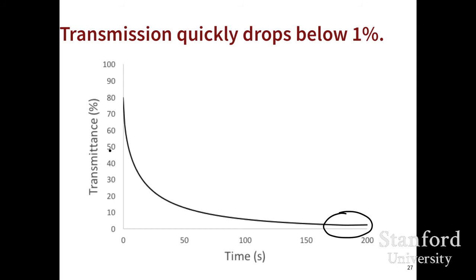And a lot of people ask what the switch time is, and that just depends on how dark someone wants the window to go. Say 10 seconds, it's already down around 30%, which is clearly darkened. But it takes a few minutes to plate enough metal to go below 1%. And this slide does illustrate that this technology has a very wide range, because we can just keep plating metal. We can make the windows go as dark as anyone wants them to go.